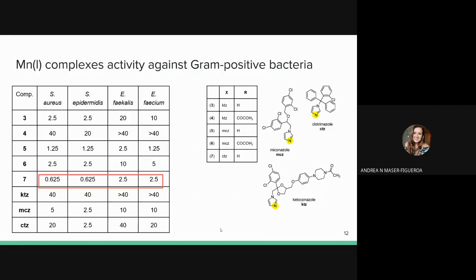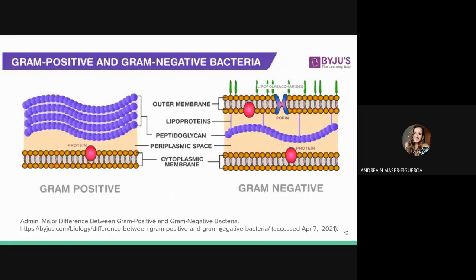Among the metal complexes specifically, the relationship was as such. The least effective was KTZ, followed by MCZ, and the most effective one was CTZ. They noticed a general trend where the activity increased in relation to a decrease in molecular weight. They compared these findings to findings from other compounds they had studied, rhodium and iridium complexes, and saw that these were more effective than the ones they had obtained. The lowest number they obtained was 2.5. In this case, they obtained 0.625. And so that begs the question, why is there such a discrepancy between the gram-positive and gram-negative bacteria?